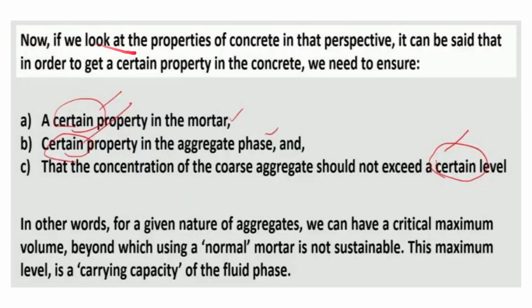Now, if we look at the properties of concrete in that perspective, it can be said that in order to get a certain property in the concrete, we need to ensure a certain property in the mortar, a certain property in the aggregate phase, and that the concentration of the coarse aggregate should not exceed a certain level. In other words, for a given nature of aggregates, we can have a critical maximum volume beyond which a normal mortar is not sustainable. This maximum level is the carrying capacity of the fluid phase.